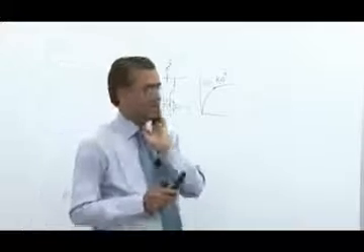So for any sheet material, the uniform strain becomes n. However, in case of sheet metal, there are two types of tensile flow instability. In case of a circular piece there is only one, but when the width of the material is greater than the thickness, like a sheet, we have two flow instabilities.